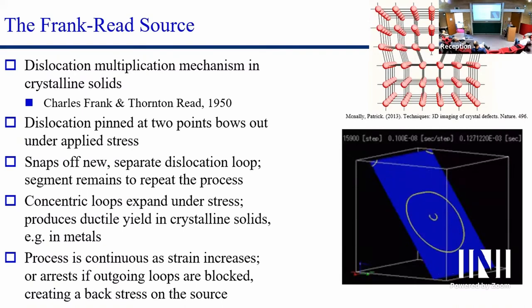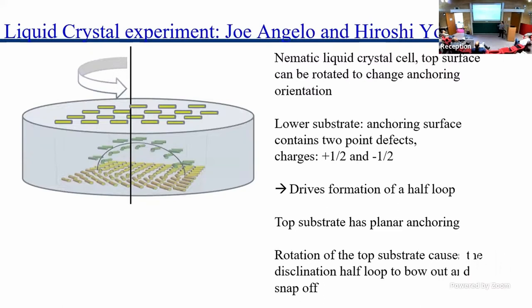Okay, so how did we come to the idea that such a thing could exist in a liquid crystal? We have a colleague at Kent State, Hiroshi Yokoyama, who had a brilliant young student, Joe Angelo, and they did an experiment where they put an anchoring condition on one substrate in a really funny liquid crystal cell where the top surface could rotate relative to the bottom surface. And so they put a +1/2 defect and a -1/2 defect on one surface and planar anchoring on the other side. Fill that with a nematic and it will spontaneously form a little disclination arch, like half of a loop.